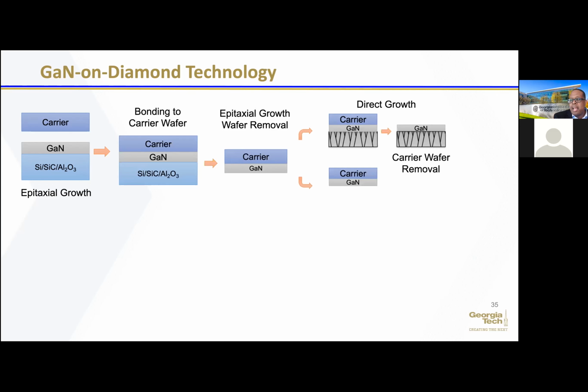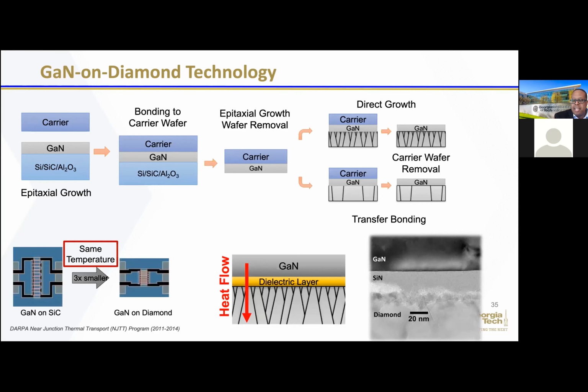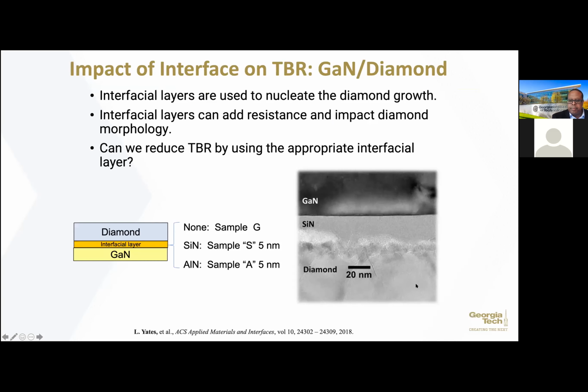In the other case, I would have this on the carrier wafer, and now I'm going to do bonding. So as I showed you before, plasma activated bonding, trying to get rid of these interfaces. And now I have a transfer bonded GaN on top of diamond. What we do see, again, these inner layers, this is what is causing a lot of the limitations in terms of moving heat from the GaN into the diamond. Even though this is a very, very high thermal conductivity material, this is what you have to worry about.